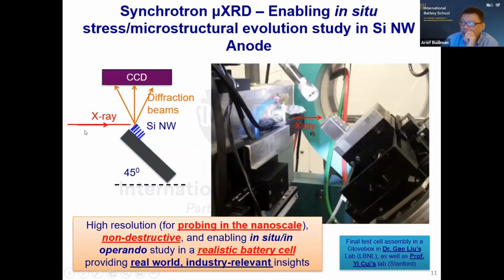Okay, the experiment goes something like this. So you have basically your silicon nanowire here, you have the battery setup. Even this battery test setup is actually a pretty ingenious work by my student, but it allows lithiation. So this is actually during lithiation, as the silicon nanowire is lithiated, we look with X-ray, and from the diffraction, we learn about what happens during that lithiation in terms of microstructural evolution, stress evolution, and performance evolution. That is kinetics.